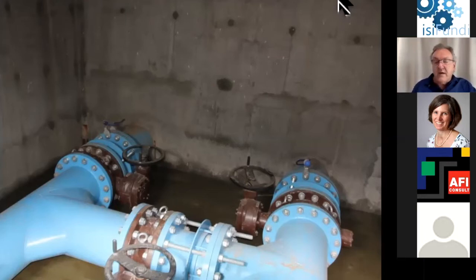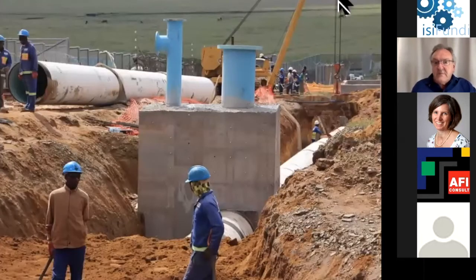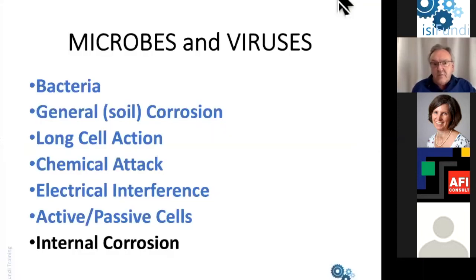If they're coupled together, then you will get quite serious corrosion of the section of the pipeline that is in soil immediately adjacent to the concrete. Sometimes this even occurs on a smaller scale during pipeline construction, where valve chambers may be encased in concrete in order to stabilize the large steel pipes. You'll note from this picture that the pipes that go through the concrete are actually coated, and this is one way of ensuring that we can in fact control the effects of this active-passive couple.